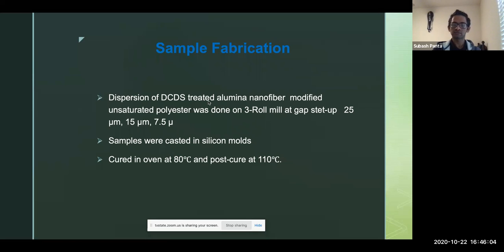Sample fabrication. Dispersion of dichlorodimethylsilane treated alumina nanofiber modified polyester was done on a 3-roll mill at gap settings of 25, 15, and 7.5 micron. Samples were casted in silicone molds, cured in an oven at 80 degrees Celsius and post-cured at 110 degrees Celsius.